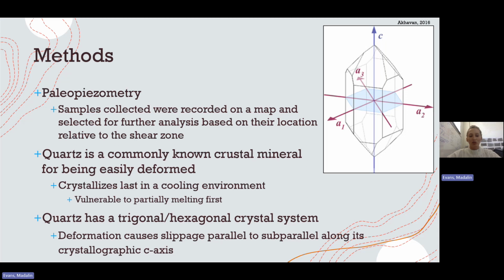Quartz is a commonly known crustal mineral for being easily deformed. The hardness, atomic structure, and lack of cleavage make it one of the more stable minerals that is highly resistant to mechanical weathering, preserving these dynamically recrystallized grains. Quartz tends to crystallize last in a cooling environment, in which it is also vulnerable to partially melting first when temperatures and pressures increase. Therefore, when deformation takes place due to these intensified conditions, quartz is the first mineral that is susceptible to being contorted. Quartz also has a trigonal or hexagonal crystal system, where deformation causes slippage parallel to subparallel along its crystallographic c-axis.